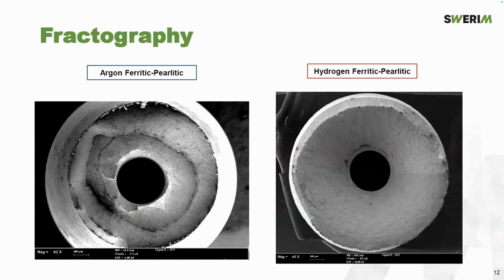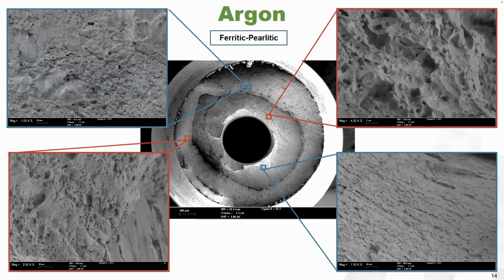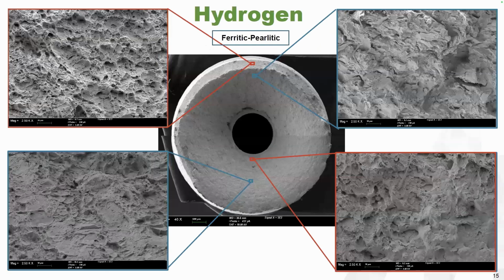If we go to fractography, it's really easy to differentiate which is with argon and which is hydrogen. The leakage zone, we would say, is this one here. And this is post-mortem fracture, because we test the specimens until leakage and then we pull apart the specimen to see the fractography. Looking more closely, we have here the martensitic ferritic bands, and here a more brittle quasi-cleavage structure.